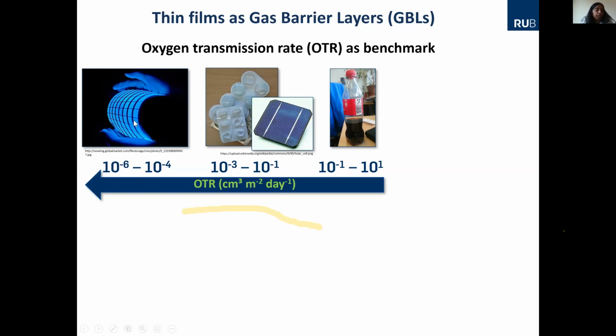So now it's not only the material, it's not only the OTR value, but also how you can coat at low temperature, because all of the packaging materials are plastics. They will not be able to withstand temperatures above 100 to 150. For example, polypropylene maybe not beyond 80. PET also maybe less than 100 degrees centigrade. So this is where ALD is the method of choice, because you can actually grow films even at room temperature as long as the precursor is reactive.